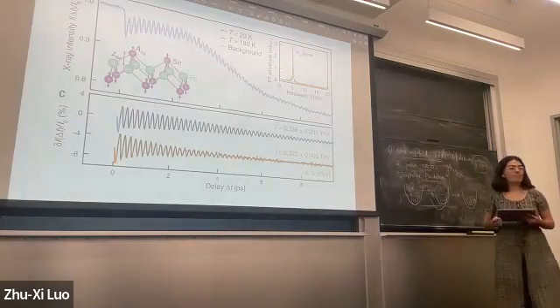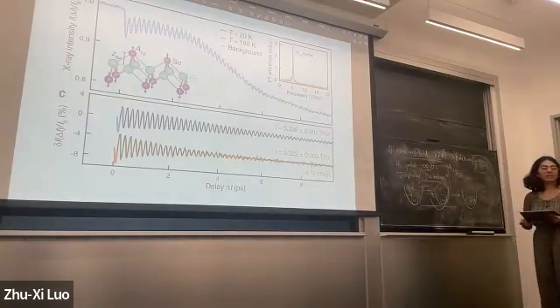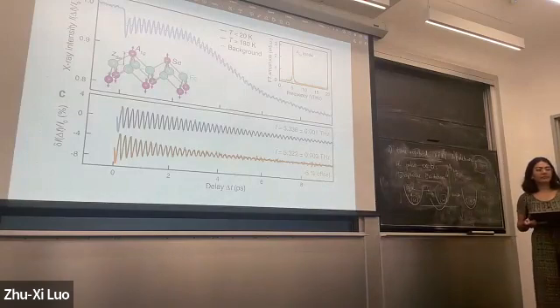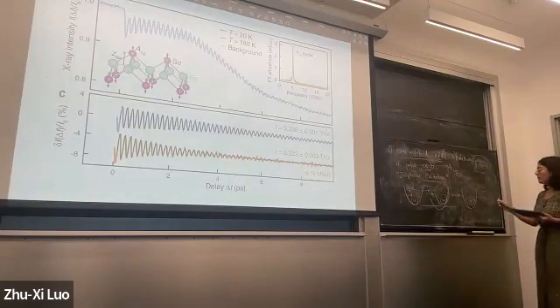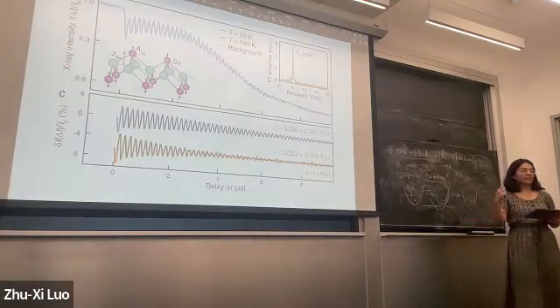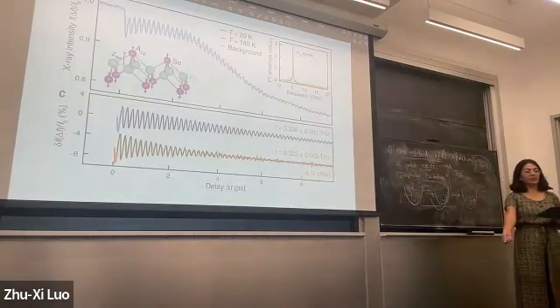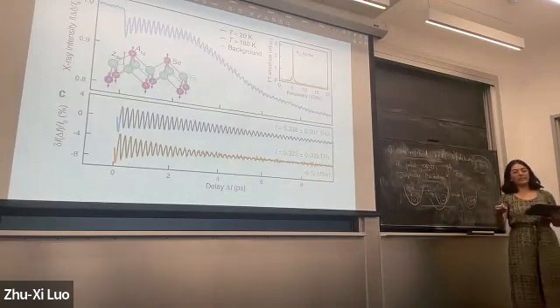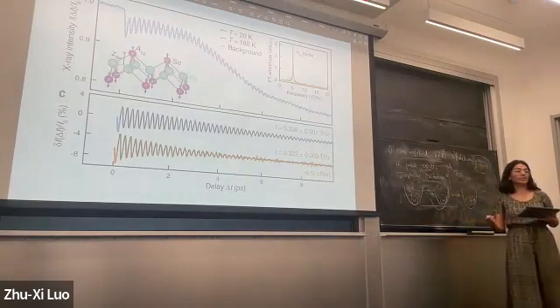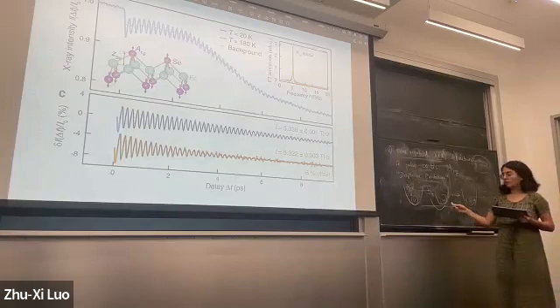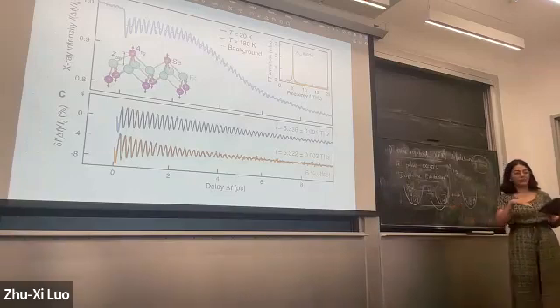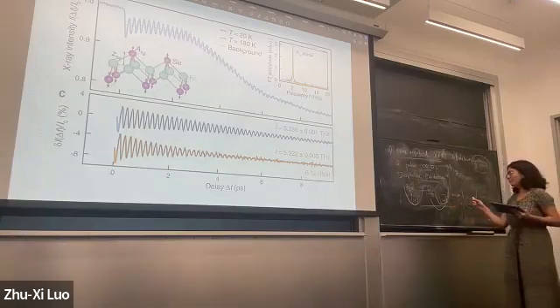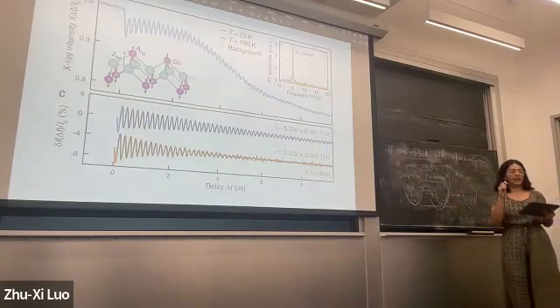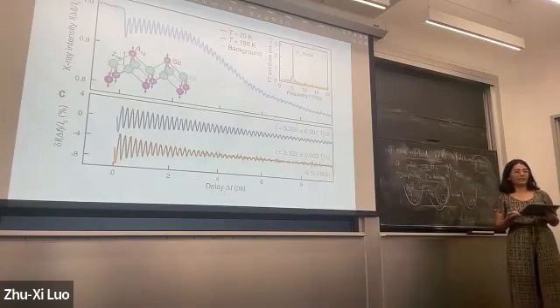So the idea is that the minimum is also determined by electrons. Yeah. So the potential profile is also changing in time. Because the electron distribution got changed extremely quickly by the laser pulse, the position of the new minimum changed too quickly for the selenium atom to get there slowly. So instead it ends up oscillating around it.